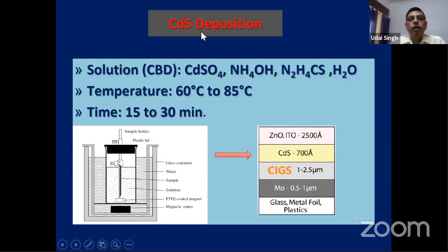Now coming to the N-type material, which is the cadmium sulfide, it is generally deposited by chemical bath deposition. Okay, so it is a simple setup where you have a water bath in which you keep a beaker. There is a coated magnet which is rotating, and you dip your substrate. In the solution, you use a cadmium source, cadmium sulfate, ammonia, and the sulfur source.